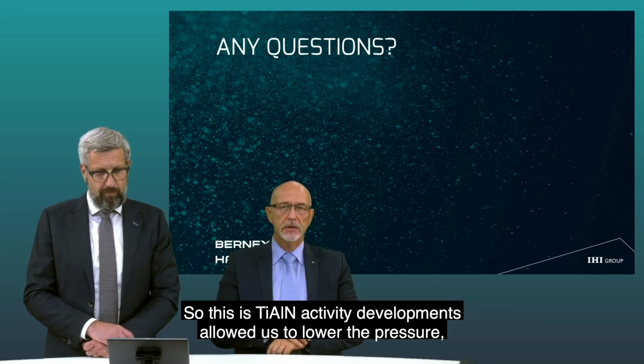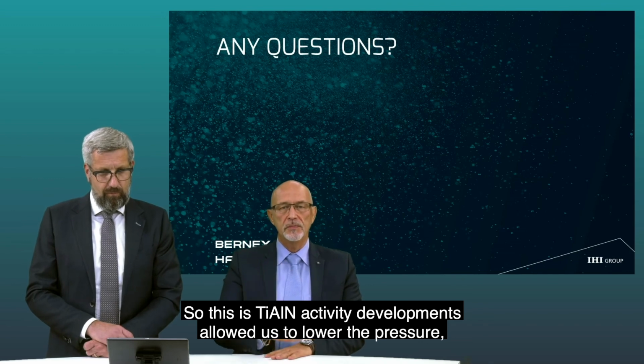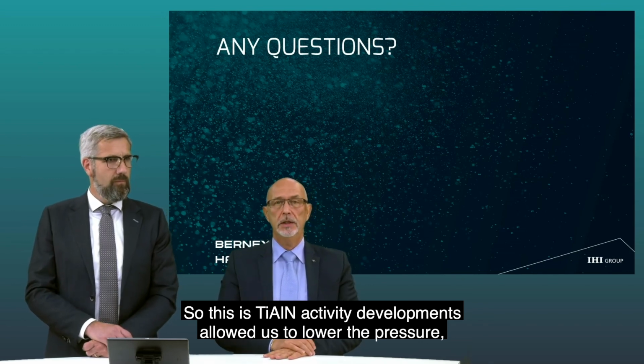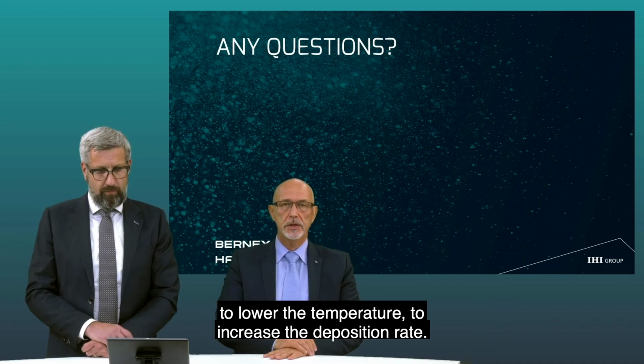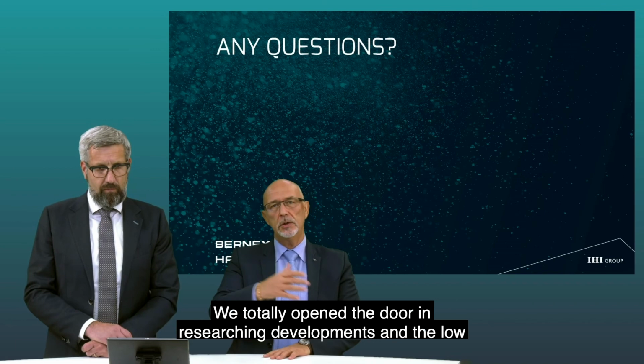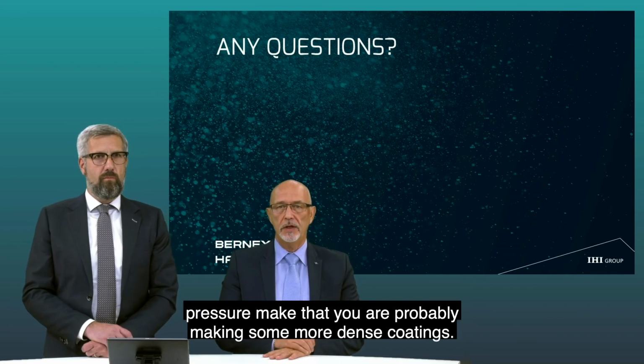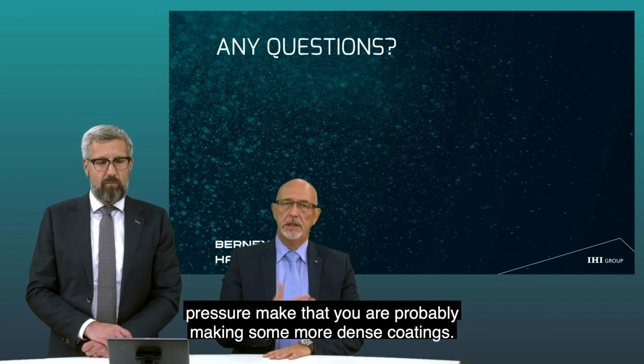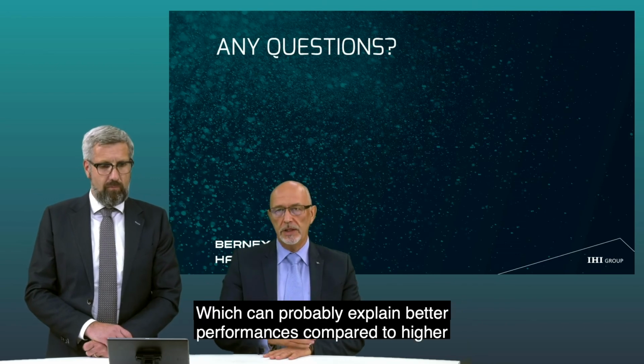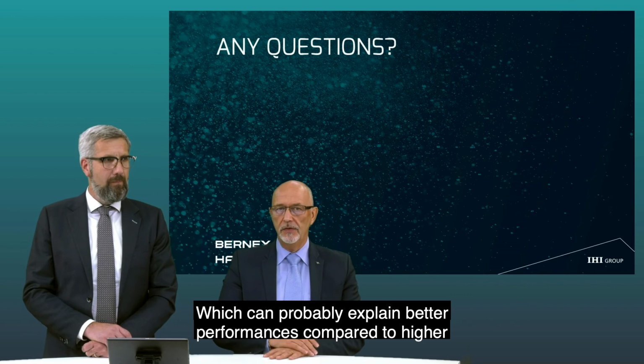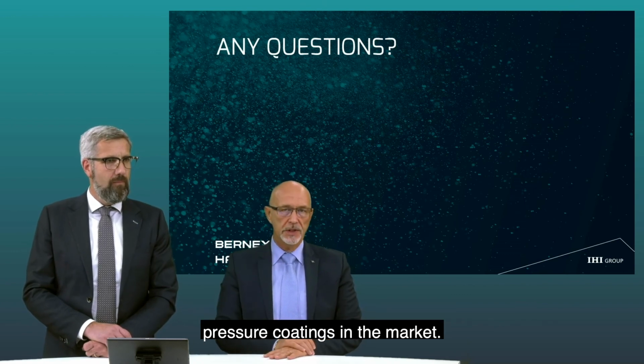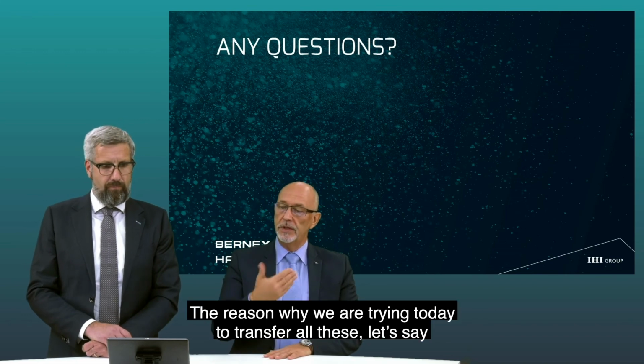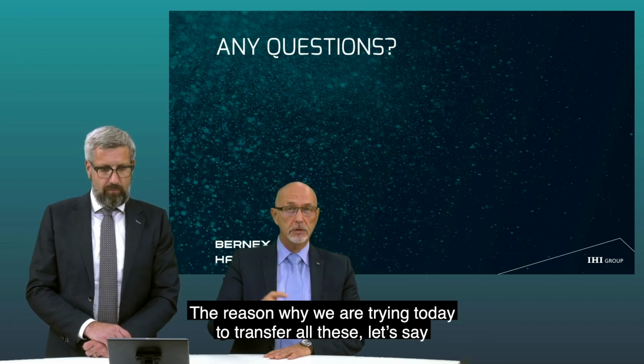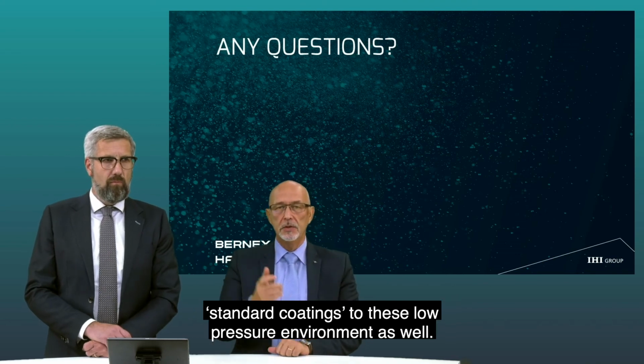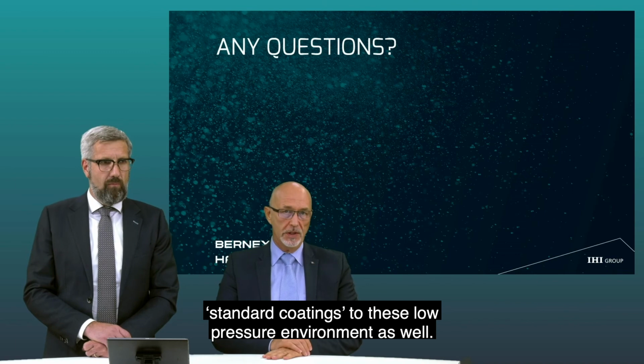And these TiAlN CVD developments allowed us to lower the pressure, to lower the temperature, to increase the deposition rate. So we learned a lot. It totally opened the door for us in the research of developments, and the low pressure probably makes some more dense coatings, which can probably explain their better performances than the higher pressure coatings in the market. That's the reason why we today try to transfer all these standard coatings to this low pressure environment as well.